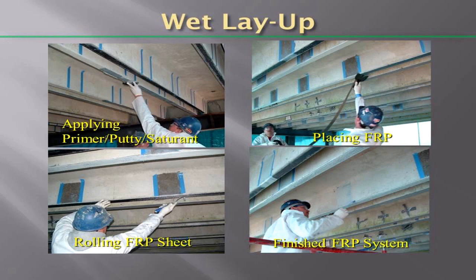When you are using wet layup for carbon fiber, you first prepare the substrate. You apply a primer, a putty, and a saturant. You place your FRP member, which has been pre-designed. You roll your FRP sheeting into your wet primer, putty, and saturant. And then you finish the FRP, typically with more saturant over the top of your sheeting to impregnate it on the structure. And then you spray a top coat. Seems pretty simple, just like rolling on wallpaper, but it's not. It's a lot more expensive than wallpaper, and just like concrete or asphalt, there are many, many ways that the material can deteriorate during the installation process.